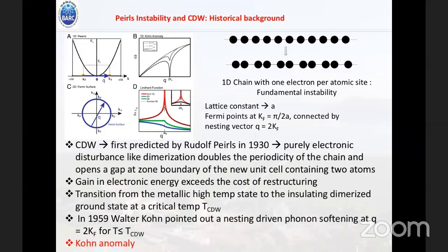I will be uttering some term like CDW. So that is the CDW of Rudolf Peierls in 1930 for a one-dimensional chain of one-electron atoms, which has a fundamental instability, where such a kind of dimerization occurs, and there is a gain in electronic energy that exceeds the cost of this restructuring. And because of that, there is a metal to insulator transition in this system, which opens up a gap at the Brillouin zone. And that happens at a critical temperature, T_CDW. So that is the CDW transition temperature. And in 1959, Walter Kohn pointed out that there is a nesting driven phonon softening at Q equal to 2k_F.